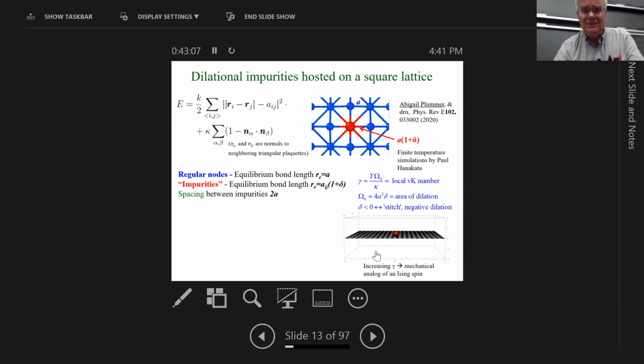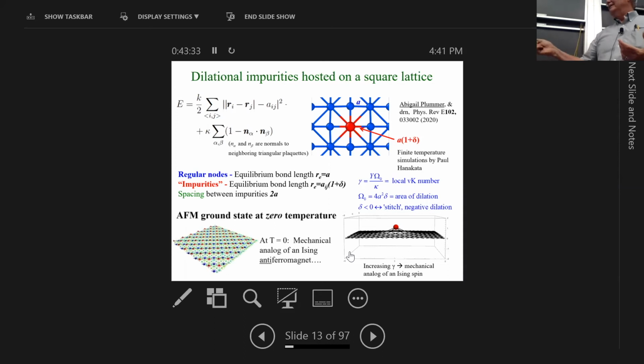And this is a simulation of one isolated such impurity. There we go. And of course, it wants to pop out of the plane, but it's tethered. It can't go arbitrarily far, and it could have gone down or up. So it has a kind of plus-minus symmetry. And if you put a lot of these into a material, say a square lattice, in a checkerboard pattern, you'll get a mechanical analog of an Ising antiferromagnet.